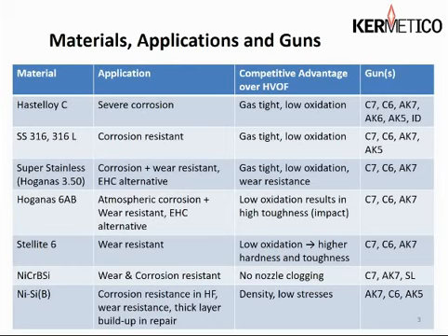Hastelloy C is very popular. We use that in a lot of refinery vessels, and I'll be talking more about that in a little bit. The coating is impermeable. We use it at 10 thousandths thickness to resist acid attack in pressure vessels. Low oxidation in the as-sprayed state, and as you can see, we spray that with every gun in our product line.